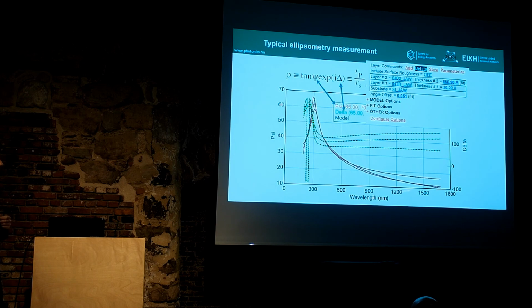I just show here typical spectra of what we measure. These are the two parts we measure. We measure the reflection coefficients for light polarized parallel and perpendicular to the plane of incidence, and one measured value is the absolute value of the ratio of these two. Even more important is this green one. This is the phase shift between the two, and we can measure it as a function of wavelength or as a function of angle of incidence. So we have a lot of data, but it's indirect, so the spectrum itself doesn't give you any clue what it is. So we need a model.